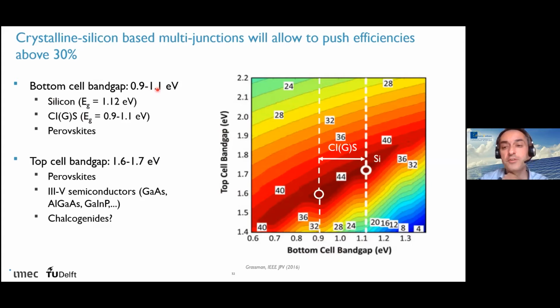So silicon is really a good material to achieve high efficiency. We can use silicon with a band gap of 1.1 as the bottom cell. Of course, other materials like CIGS could also be used. And then we see that the top cell should have a band gap of around 1.6 to 1.7 eV.